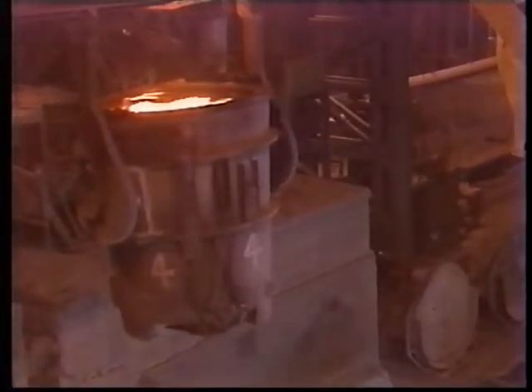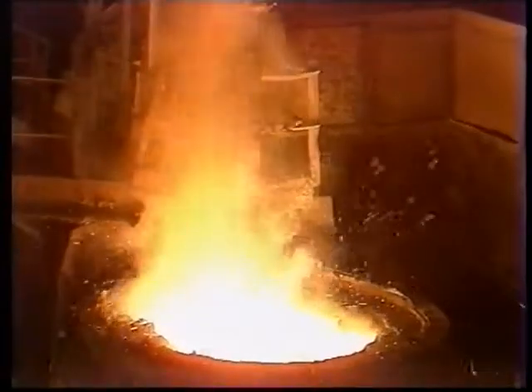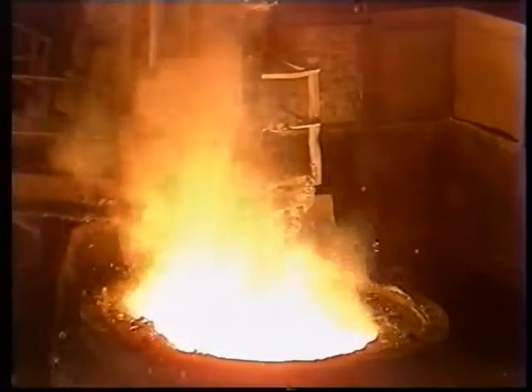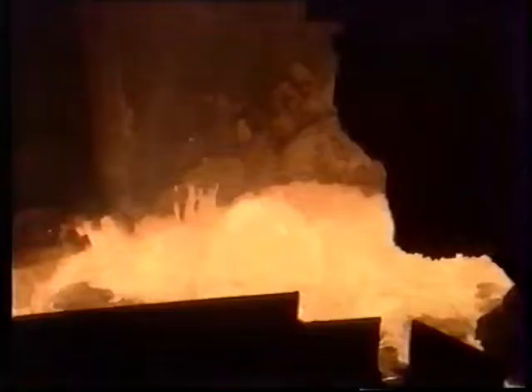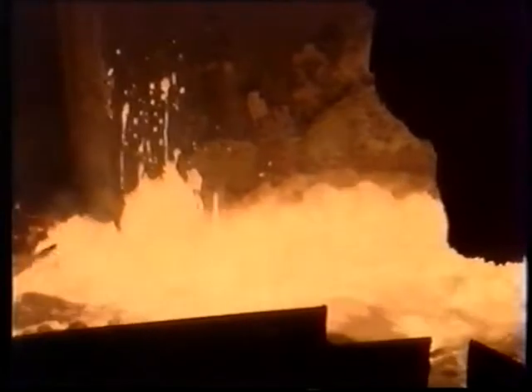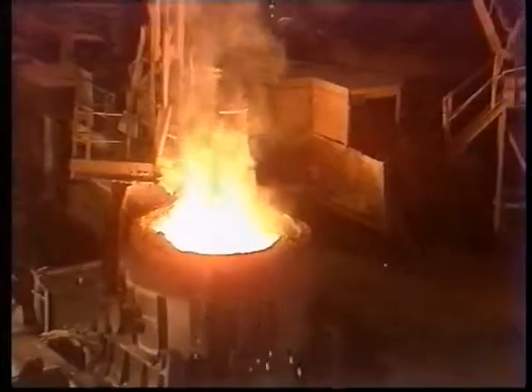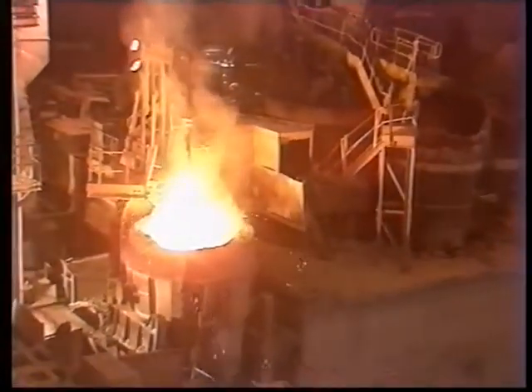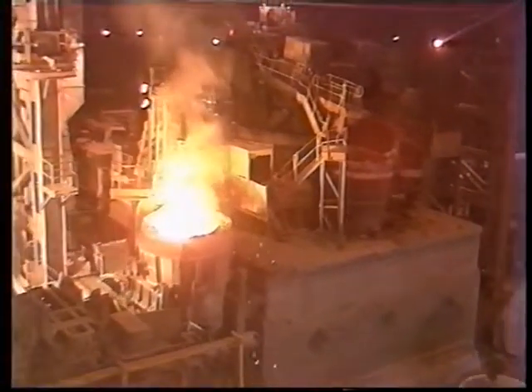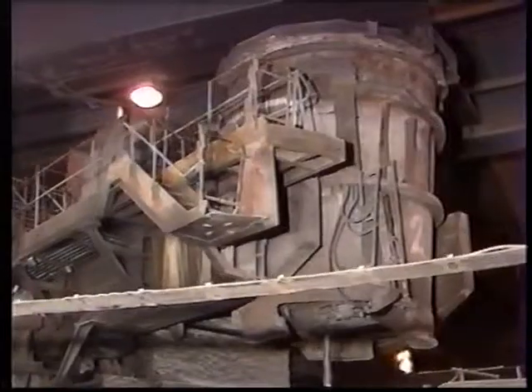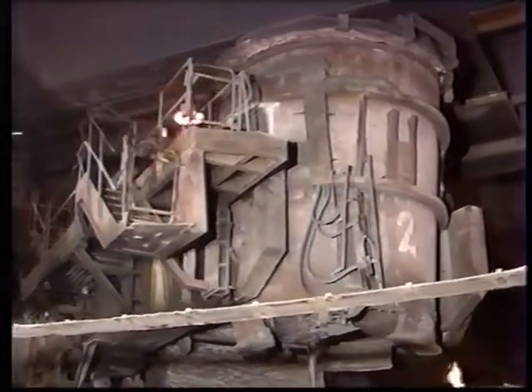Once the AOD vessel has been tapped, the cast then passes to the flushing station. Here it is stirred with pure argon, using either an injection lance or porous plug in the ladle bottom to achieve the correct uniform casting temperature, which as a process requirement must be controlled within a 10-degree band.